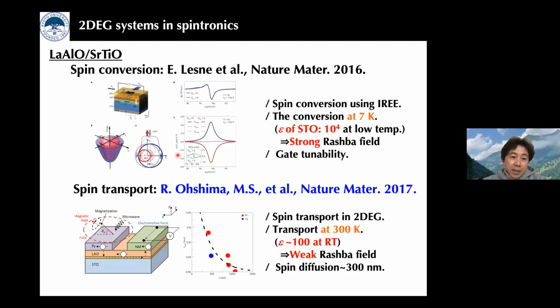Here the point is that strontium titanate is insulating. We can apply a gate electric field to the 2D system. And as I previously explained, the spin conversion can be realized by the large Rashba field. And in addition, the spin conversion is gate tunable. And the group in France nicely demonstrated the gate tunable spin conversion in oxide 2D systems.